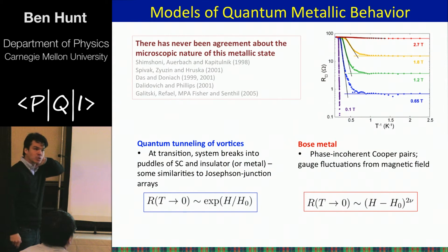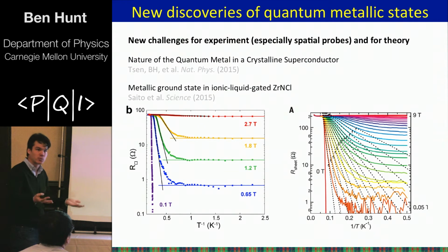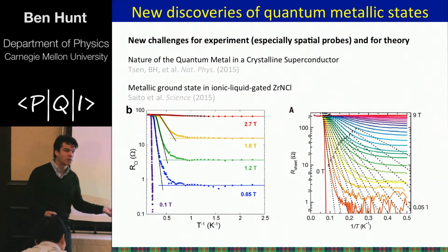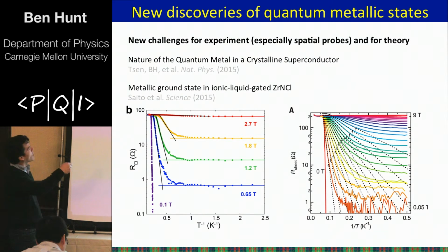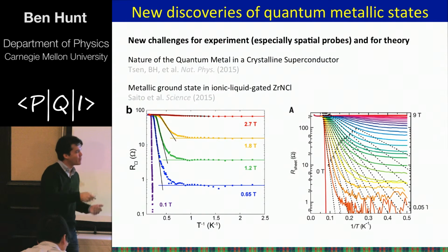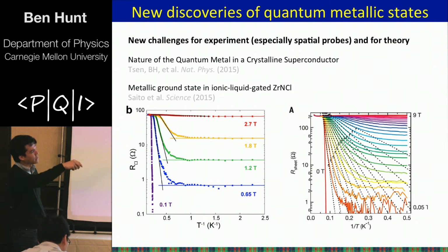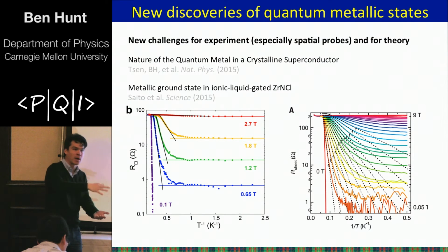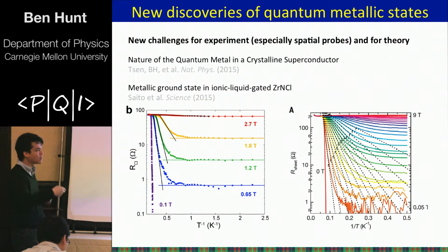Particularly spatial probes. We can now access the two-dimensional superconductor quite easily with scanned probes. So looking at, say, shot noise tunneling might be a very easy way to confirm whether we're seeing 2e charge or e charge. I should point out that these metallic phases seem to be showing up more and more these days. Here's a paper from Japan in which they've created a 2D superconductor by ionic liquid gating a semiconductor. And indeed, they see a very similar behavior to ours.